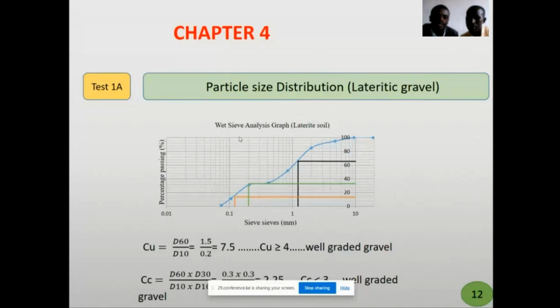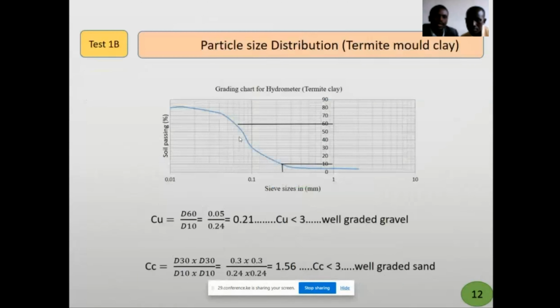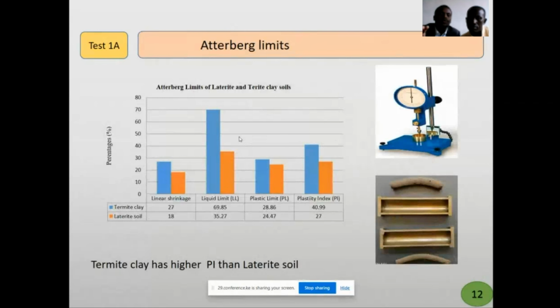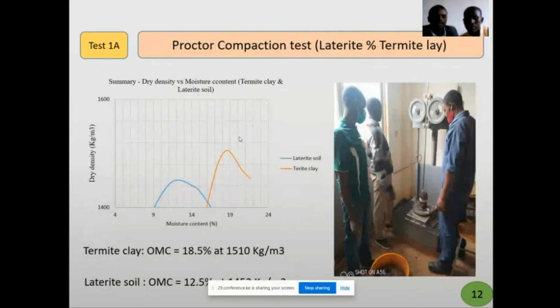After the research and the tests, we made the observations of this project. For the particle size distribution, we found that the laterite was well graded, and the clay soil also had uniform and well graded particles. When we come to the Atterberg limits, we compare the linear shrinkage, liquid limit, plastic limit, and plasticity index of our materials, whereby we find that termite clay generally has a higher PI than the lateritic soils. On the optimum moisture content, termite clay has 18.5% at 1510 kilograms per cubic meter, and the laterite soil has 12.5% at 1453 kilograms per cubic meter.